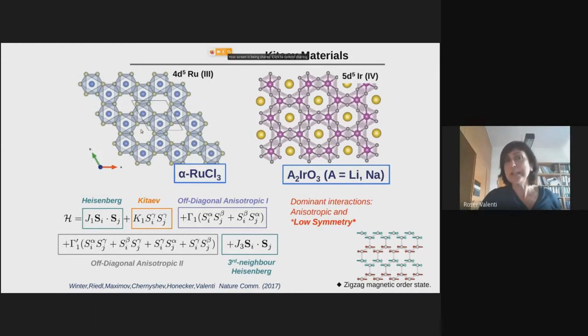Again, you find this honeycomb lattice, and they basically build layers of honeycomb lattices. Now if you look at the spin interactions in this system, what one finds is that indeed the Kitaev interaction is the dominant one, but there are other interactions that are non-zero, and these materials are not spin liquids. They, in fact, order magnetically, and this is due to these extra interactions. So indeed, one calls them candidate Kitaev materials, but they are not perfect Kitaev. We don't have with these systems the realization of the spin liquid. How can we do that?